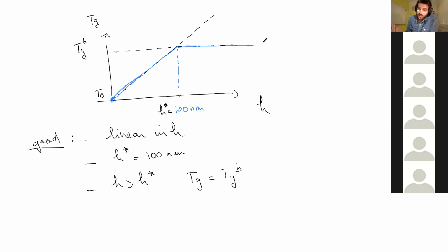But there are drawbacks. What is bad in this model is that N does not matter. The size of the polymer chain doesn't matter, which is not observed experimentally. Experimentally, if you have one molecular weight or one size of polymers, you have one depression. If you change the molecular weight, you have another line with a different slope. So the slope is depending on the molecular weight, on capital N. And in this very simplified picture, this is not the case.